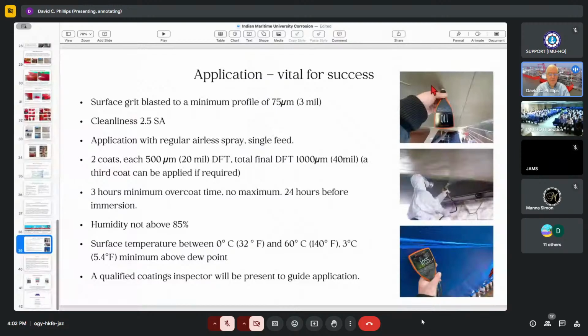Good. All right. So the first thing that you need to do to get this kind of result of preventing corrosion with the right kind of coating is you've got to prepare the surface properly. This means, in this case, with this kind of coating, you need to have a rough surface. It's got to be 75 microns, which is 3 mil roughness. And this is very important. Without that roughness, it will not last.